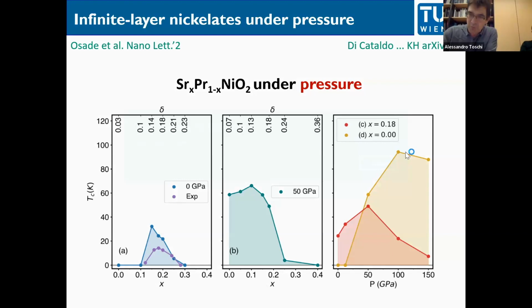That is a good question. So it's still the situation that these pockets are not very strongly correlated, but they grow. And at one point they grow and it becomes maybe a little bit more questionable, but not so questionable that we wouldn't think that the TC will increase and that you will get enough hole doping to make it superconducting. So if you go to 200 gigapascals, then this pocket will even touch the x squared minus y squared orbital. And in this situation, for sure, at the latest, the single orbital description breaks down.